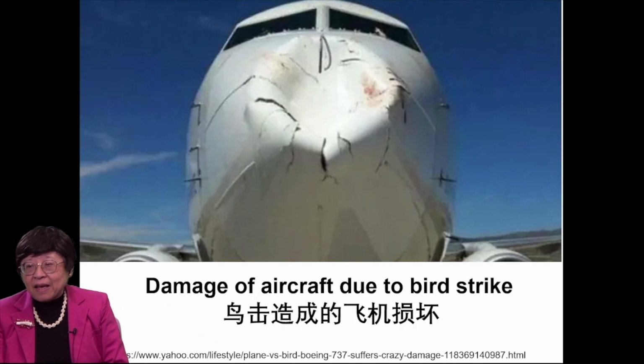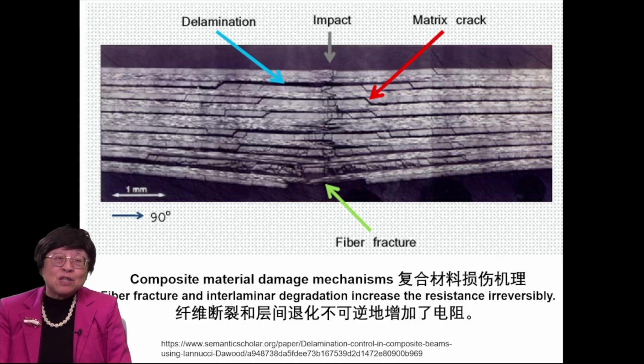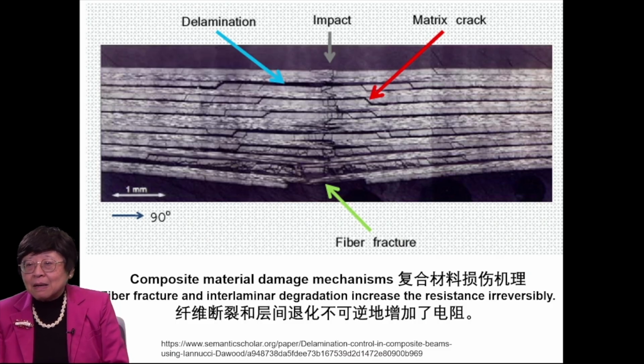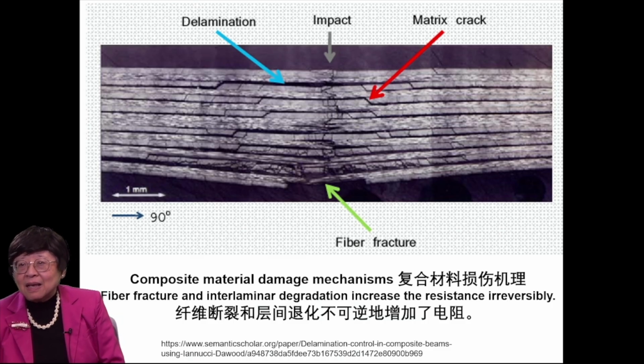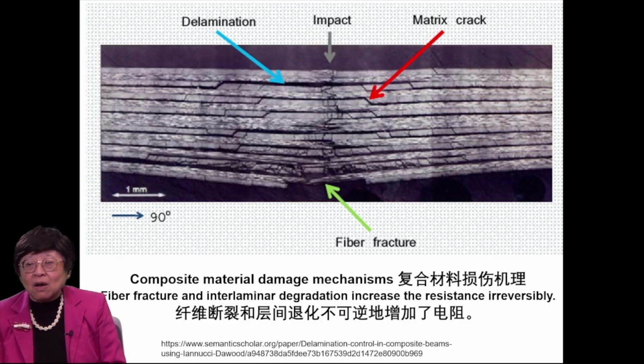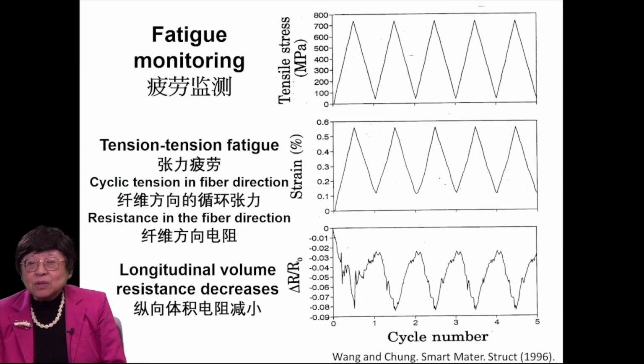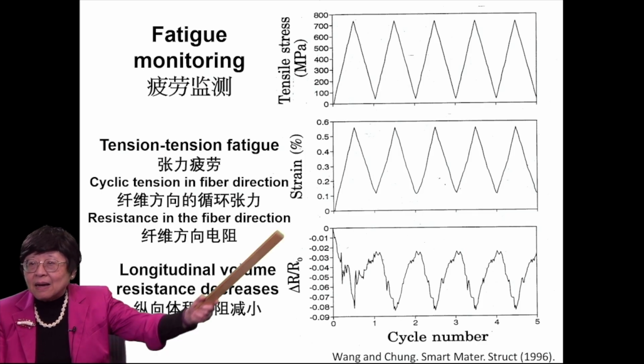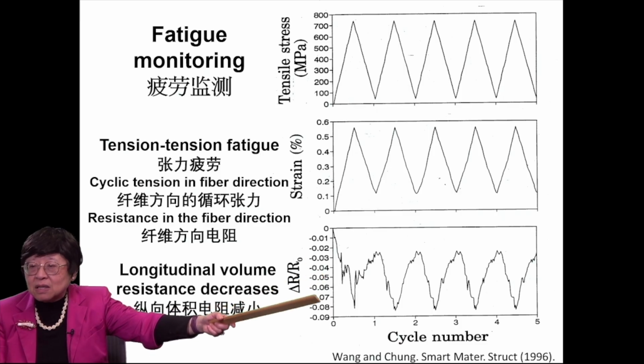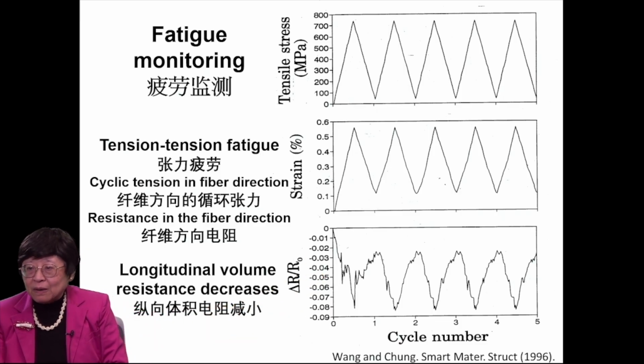Now, damage of an aircraft can be due to bird strike and hail strike and so on. So damage monitoring is important. Composite material damage mechanisms include fiber fracture as well as interlaminar degradation. Both of these mechanisms cause an increase in the resistance, and it's an irreversible increase. So we can use the resistance measurement to monitor fatigue. This is tension fatigue with the tension applied in the fiber direction and the resistance measured in the same direction. And we see that every time one tensions, the resistance goes down, as I explained before.